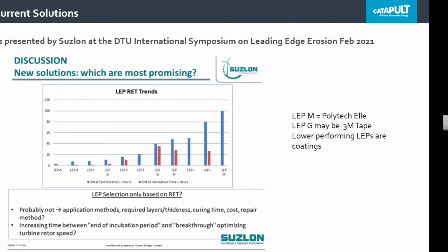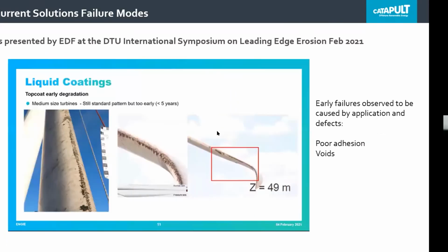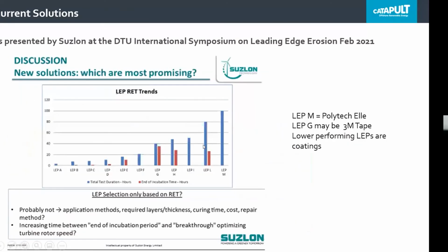They also presented an overview of the rain erosion test results. What you can see is at the lowest, some of these products in rain erosion tests are performing at around 4-5 hours, which is exceedingly low. I would say that current coating systems are around 20 to 30 hours, of those that are on the market, and actually ones that are in development are getting higher than that.